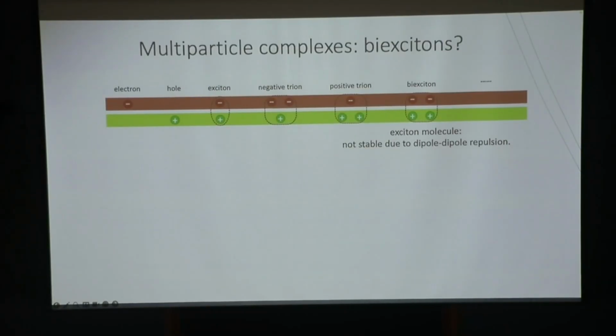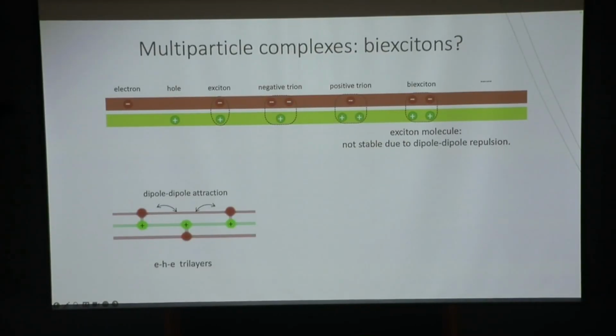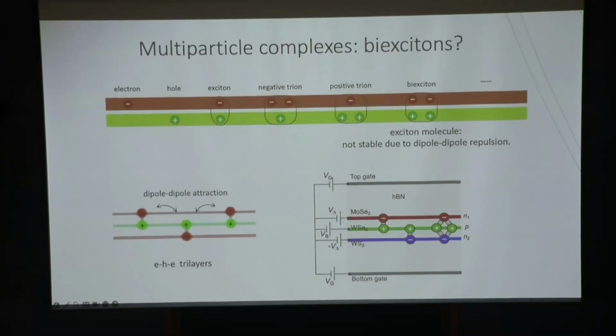How about biexcitons? If we still have 2 layers, it turns out that these 2 excitons cannot form molecules, because they both have an electrical dipole pointing, say, downwards. They have the same dipole, so they repel each other and cannot form a bound state. However, we can make use of the flexibility of van der Waals heterostructures to make a 3-layer system. Now, if you introduce an electron-hole layer and an electron layer, you can form one type of exciton with a dipole pointing down, and the other exciton with a dipole pointing up. Now, if you have opposite dipoles, they will have an attractive interaction, and they will happily form this kind of excitonic molecular state.